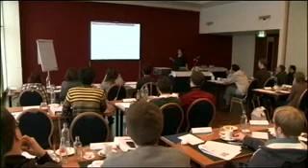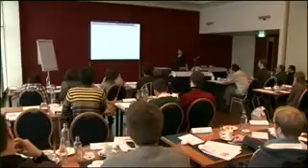This is data from the thesis of Vanessa Kocaba, where we studied how these different phases reacted in detail. You can see, of course, there's a lot of variation from one cement to another, but we have the same general pattern. Here, this is the C3S, the alite phase. You can see by 10 days, this has reacted about 80 or 90%. So it's almost all reacted in the first 10 days. In very stark contrast, it seems the belite hardly starts to react before 10 days.